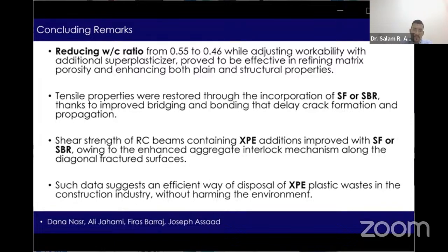SBR respectively. The tensile-related properties were recovered with the addition of steel fiber and SBR due to improved bridging and bonding that can delay the formation and propagation of cracks. The shear strength of reinforced concrete beams containing XPE waste improved with the addition of steel fiber and SBR due to the enhanced aggregate interlock mechanism along the diagonal fractured surfaces.